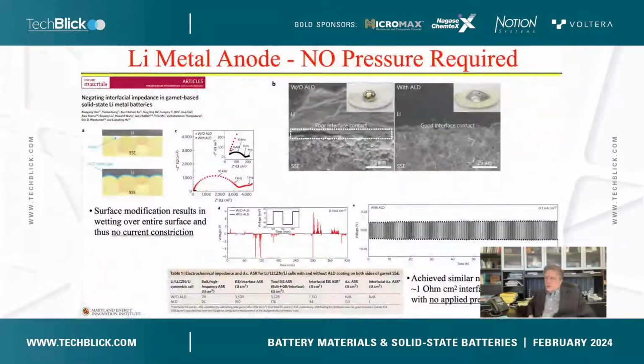So to start off, we worked towards getting the lithium metal to wet the solid electrolyte interface. This is work we did some time ago, published in Nature Materials, where you can see if we just take a lithium foil and put it on a garnet disc and heat it up to the melting point, it just forms a ball. It's the classical non-wetting. But if we put a very thin atomic layer deposition of alumina on it, it will wet and form a conformal surface.